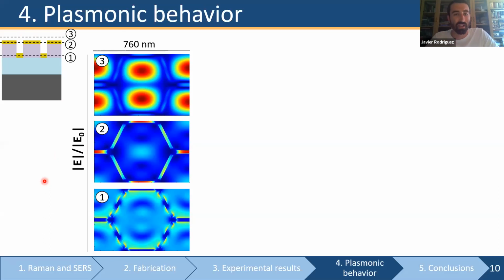So first of all, if we take a look at the peak that is of the most interest for the Raman, for the SERS, we can already see something very interesting. Here, what you're seeing, as Amilcar said before me, is a collective excitation of the system. Why? Because you can see a pattern that is not following the position of the elements, but it's following the symmetry of the lattice. And what is more important, you have this pattern outside of the structure. So this electric field distribution, this collective excitation, is able to probe the molecules that would be sitting on top of the structure.